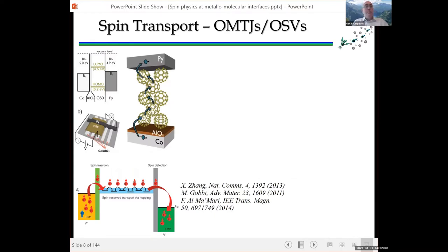Again, because it's a carbon allotrope, it has no hyperfine interaction, or the only hyperfine interaction is coming from the carbon-13 isotopes, 1.1% of the atoms in the fullerene. And because in theory it is only composed of carbon, a very light element, the spin orbit coupling should be small. Although because of the curvature of the molecule, it is quite in question whether the spin orbit coupling is really low or not.